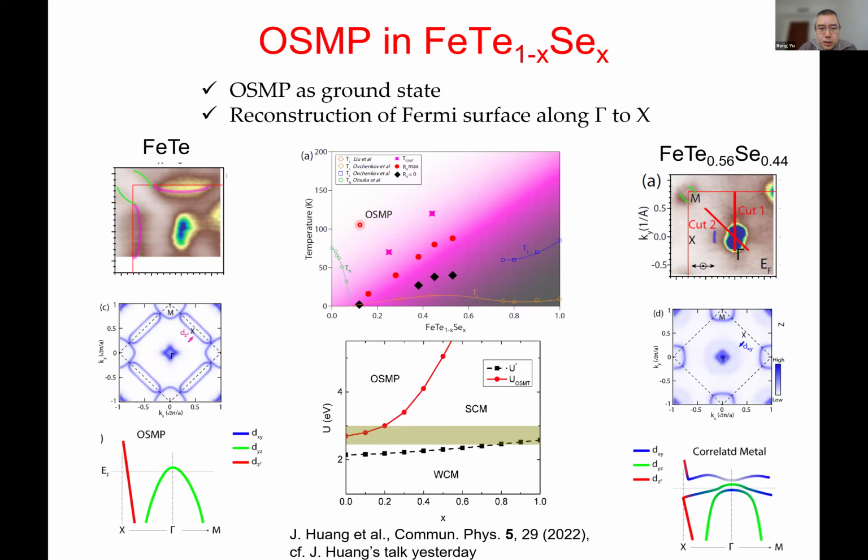Here I show just a cartoon with a two-orbital system. In this orbital-selective Mott phase, the electrons in one orbital are all Mott localized, and in the other orbital, the electrons are still itinerant and behave metallically. In experiment, this can be measured through the mass enhancement factor, which should show very different values for different bands when they are dominated by different orbital characters. This orbital-dependent mass enhancement factor can be seen as a precursor to the orbital-selective Mott phase. To understand the orbital selectivity and orbital-selective Mott behavior theoretically, we consider a multi-orbital Hubbard model.